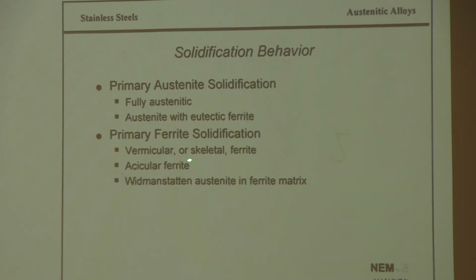And these are different types of ferrite that will be formed. Down here you get something called Widmanstätten austenite in a ferrite matrix. That's where it pretty much solidifies all the way as ferrite, and then at the very bottom, sometimes along the grain boundaries, you get a little bit of austenite that reforms, and that's called F-type solidification.